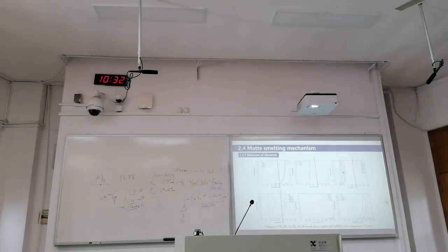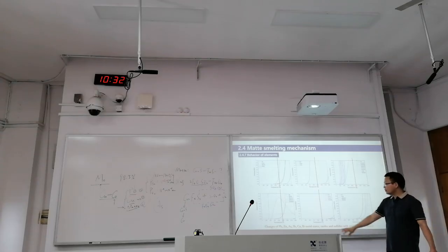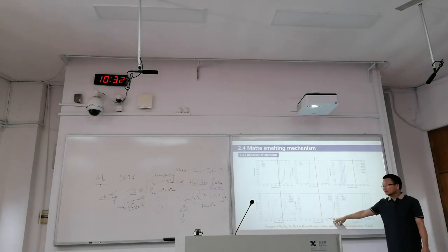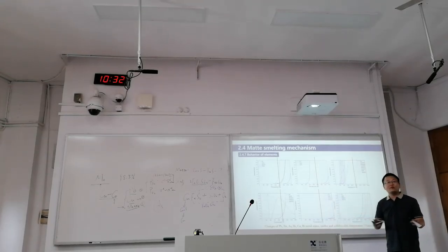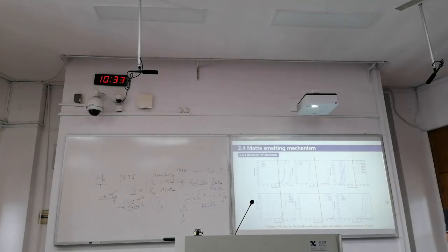Let's try to check it. Same story. Oxides will recognize. So this is 1, 2, 3, and I have put copper in the middle of the bottom row. So we are finding that at the temperature of copper making, nothing will be lost to the gas phase. Copper, metallic form, oxides, sulfides, they will be in melted form or solid form. So there will not be too much loss. And for crystals, same story.